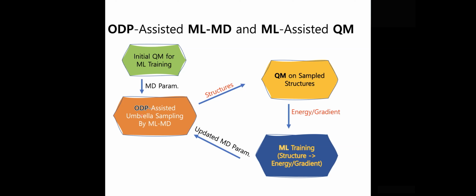At about 7 or 8 iterations, we probably have pretty good molecular dynamics parameters through machine learning. And there is yet another check: you do the machine learning training for each iteration, which is essentially just comparing the exact values and the predicted values, right? That gives you data accuracy. So the first one is chemical accuracy, and the second one is data accuracy validation. So we have a dual validation. According to our simulations, about 7 or 8 iterations is good enough.